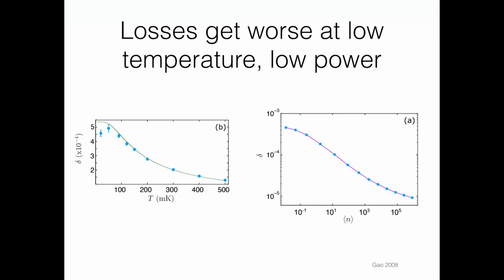The other kind of weird fact about losses in superconducting circuits is that they get worse at low temperatures and low microwave power, which is the parameter space that you need to be in to do qubit operations. You have to put in, on average, 1 photon at a time, and you have to go down to millikelvin temperatures. So this is a plot of the loss tangent, so higher is worse. And as I turn the temperature down below hundreds of millikelvin, you see that it blows up. And then also, if I turn up the microwave photon power, I can make this loss kind of go away.